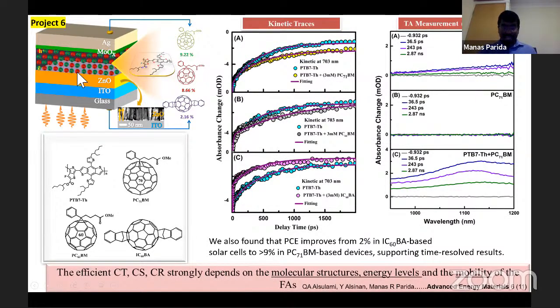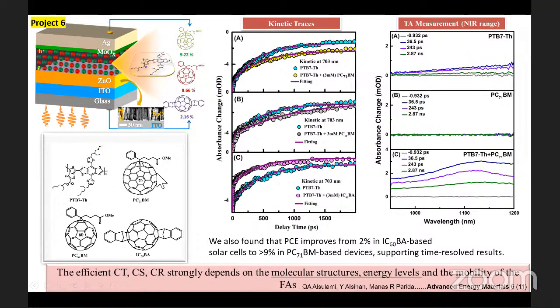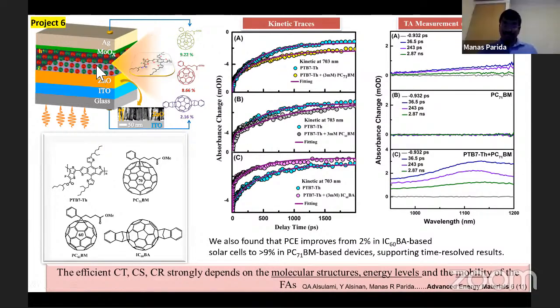So you can take your starting material inside here, and then you play with what type of electron transfer layer and hole transfer layer you are using, and then you need a transparent substrate where you can pass the light. So we play with three different fullerenes, like carbon 60, carbon 70, carbon 61, and this depends upon the energy difference with this particular donor. We saw we have a better efficiency at carbon 70, like 9.2%, and a lower efficiency with the other two. Only the ICBA, which is a different acceptor, gave the lower one.